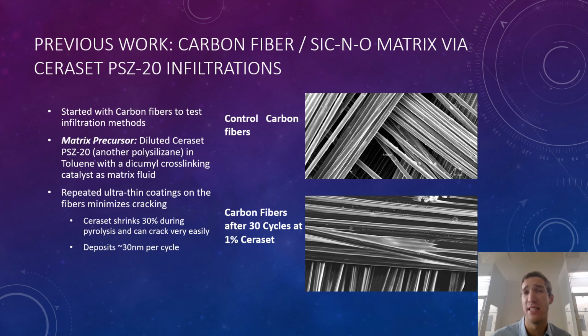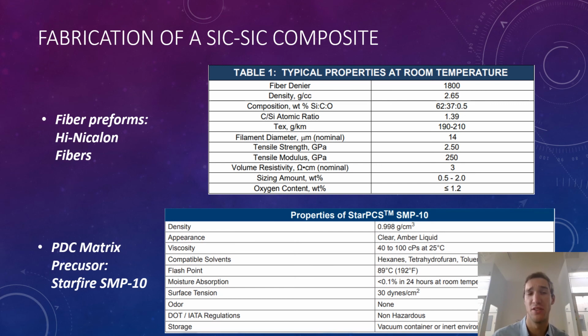Some previous work that I did earlier on in this project is working with carbon fibers and then Ceraset as the infiltration agent, Ceraset PSZ-20. As you can see, the control carbon fibers and then the 30 cycles at 1% Ceraset infiltration. There are 2 reasons we moved from Ceraset to the SMP10, as you can see on the bottom half of this SiC-SiC composite fabrication slide. The Starfire SMP10 reduces down into an almost pure silicon carbide residue, which is what we're looking for. We're looking to create here a silicon carbide ceramic matrix composite. The other reason we moved away from Ceraset is because it's no longer commercially available.